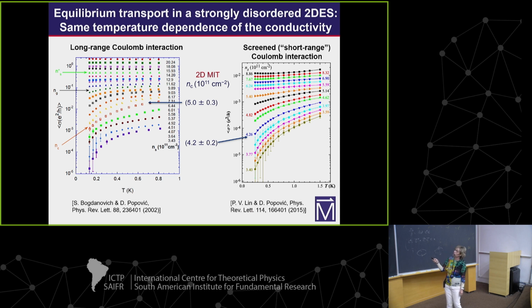This is something that has been known forever in strongly disordered silicon MOSFETs. Then as we reduce the density, the temperature dependence becomes insulating-like, and at some point we get to the metal insulator transition. Vlad discussed in his talk yesterday examples of other materials where the metal insulator transition does not take place, where there's a change in the sign of the temperature dependence, but at much lower densities.